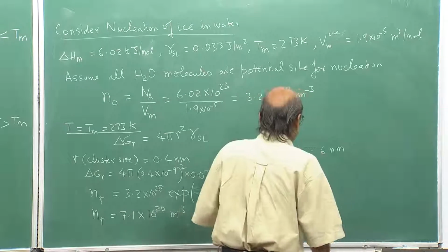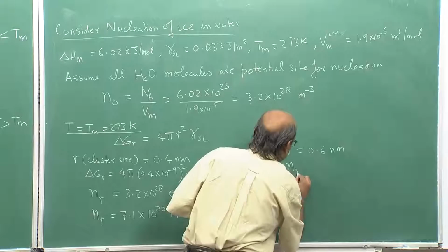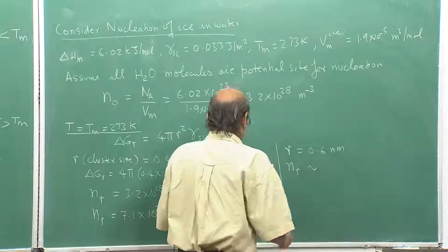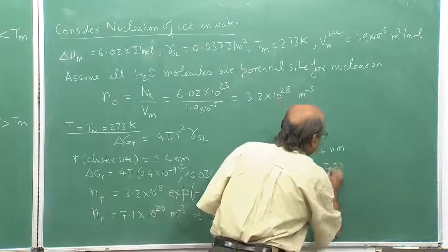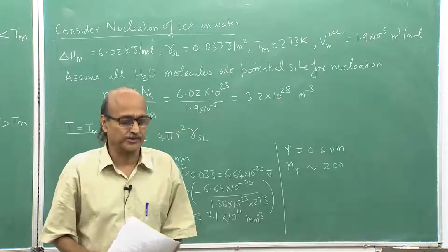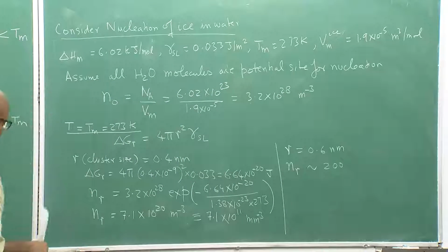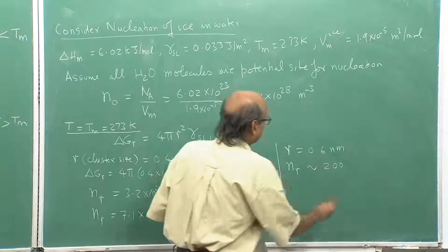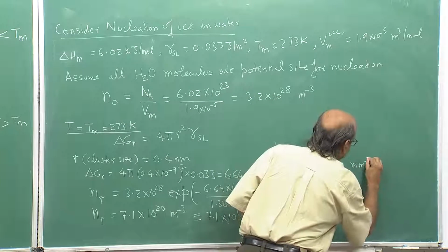I will get n_f to be of the order of just 200 per millimeter cube.